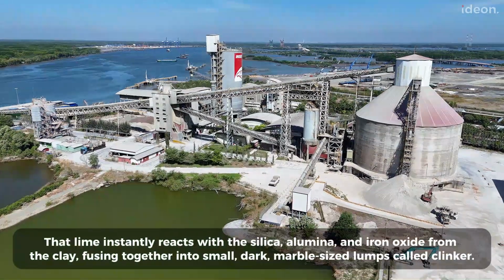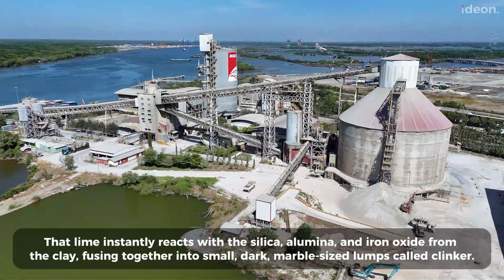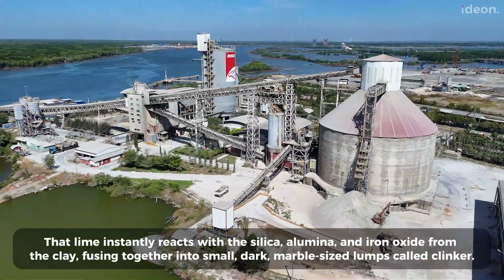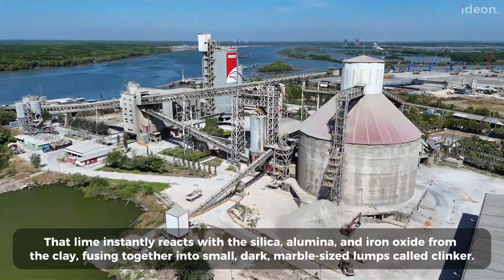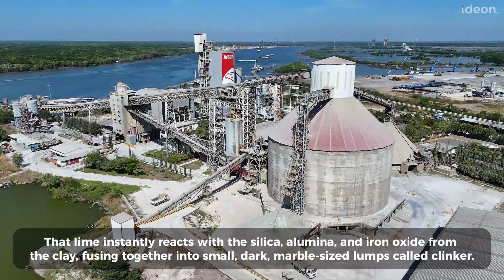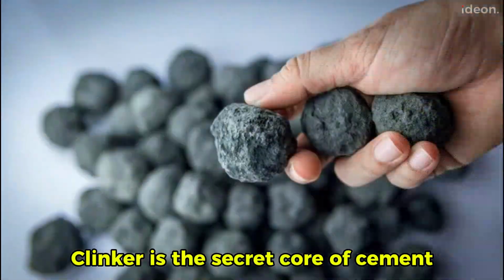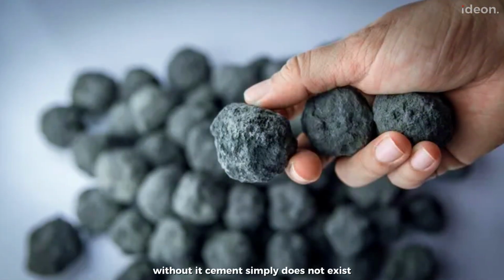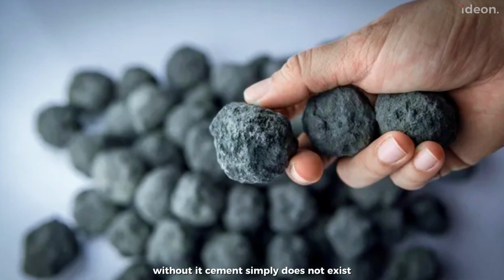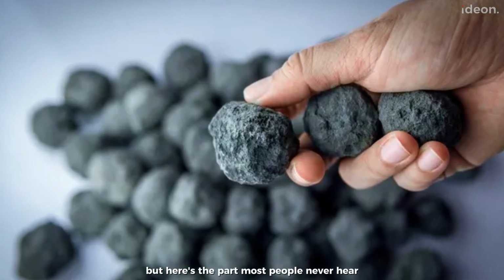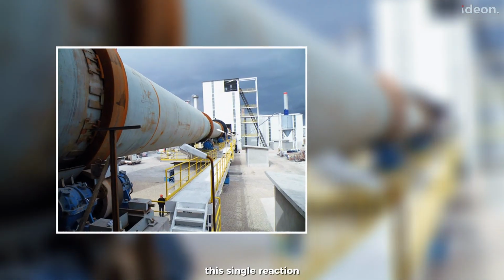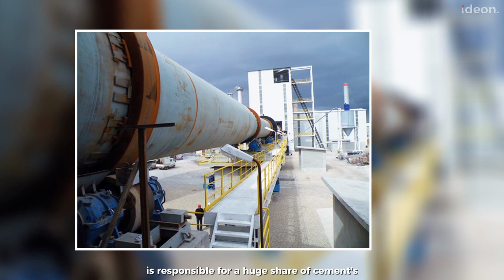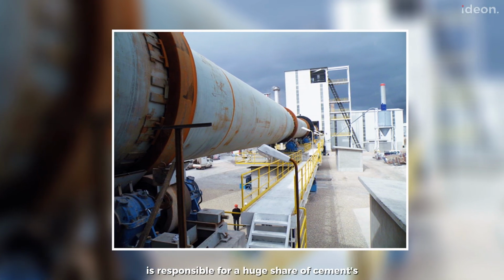That lime instantly reacts with the silica, alumina, and iron oxide from the clay, fusing together into small, dark, marble-sized lumps called clinker. Clinker is the secret core of cement. Without it, cement simply does not exist. But here's the part most people never hear. This single reaction, limestone breaking apart inside the kiln, is responsible for a huge share of cement's carbon footprint. We'll come back to that.